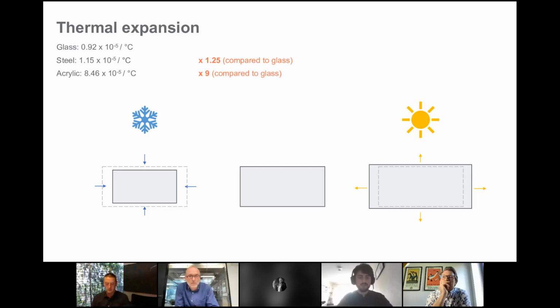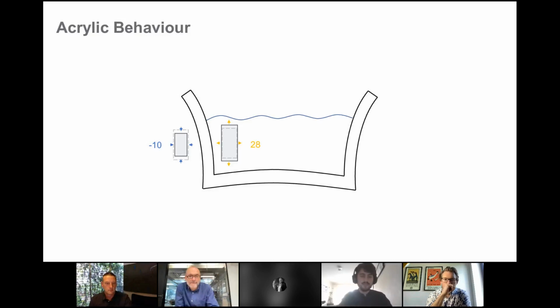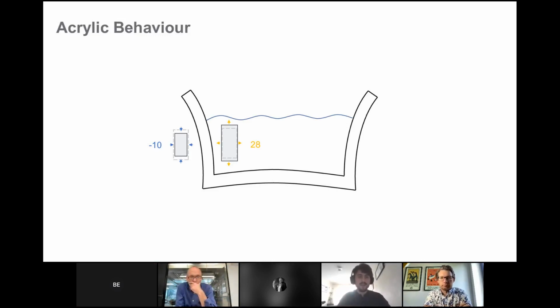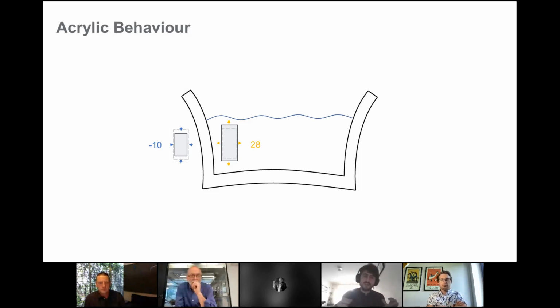Just to be clear, here we've got a piece of acrylic in the middle, and when it's cold, you see it shrinks. When it's at hotter temperatures, you'll see it grows. One of the interesting ways this manifests itself is we've got hot water, 28 degrees, inside the pool, and on the outside, on a winter's day, maybe the middle of the night, you'll get like -10 degrees Celsius. So on the inside, the acrylic is trying to grow, and on the outside, it's trying to shrink. So you get this weird bowing effect. We actually saw this in one of the first weeks of it being built. Validating our calculations, we saw a significant 80 millimeters of the top moving out. That was one of the interesting things about this pool and the design.